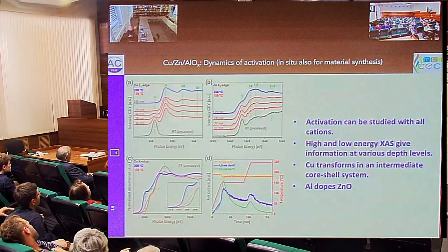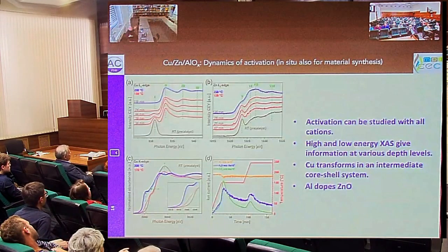And the rest of it is also important that we found. The critical issue is that you see that zinc carbonate is involved in the catalyst synthesis. And then you think, now, you take the zinc oxide, charge it with CO2, what will happen under reaction conditions? Of course, the zinc carbonate will form again. That means the interplay between zinc carbonate and zinc oxide that you see in diagram B is also a descriptor for the function of this catalyst.